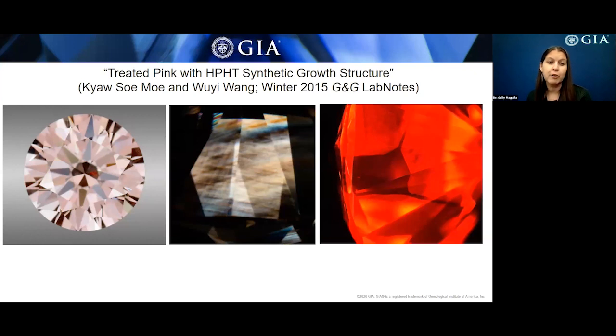Therefore, their growth rates are quite different from natural diamonds. And typically, the growth structures we see in HPHT lab grown diamonds are diagnostic for that growth method. However, there can be exceptions, and this stone is one such exception. GIA's New York lab examined this pink diamond that had a growth structure similar to HPHT lab grown diamonds.